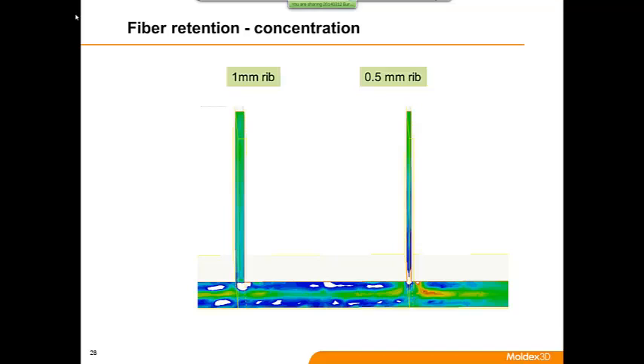So we can see on the right corner, there's a red region over here. And also inside the rib, you will see at the very beginning a lot of blue colored area, which means you have a less concentrated fiber distribution over there. So this is a very valuable tool for designers to think about the rib thickness, because maybe the rib thickness is fine even up to the structural analysis. But during the actual manufacturing, the workers, the technicians will always have trouble getting those fibers into those regions. That's not related to the material itself, that's not related to the process, but still it will trace back to the original design of the geometry.